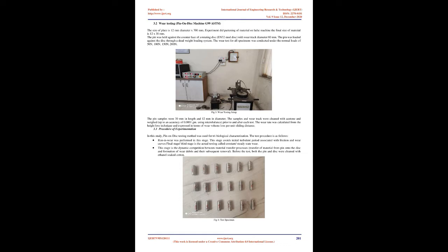1985, a load velocity diagram is plotted that indicates the beneficial effect of silicon content on resistance to severe wear. The onset of severe wear occurred at a characteristic transition load, at which a small quantity of aluminum adhered to the steel disc. This transferred deposit grew in size and initiated gross plastic deformation and fracture of the aluminum alloy pin as the test progressed.